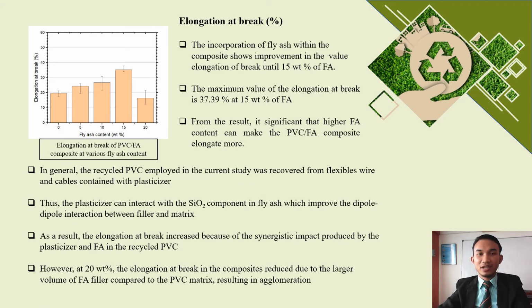Next, I will share the result of elongation at break in my study. The incorporation of fly ash within the composite shows improvement until 15 weight percentage of fly ash. The maximum value occurred at 15 weight percentage of fly ash, which is 37.39%. From the result, it is significant that higher fly ash content can make the composite elongate more.